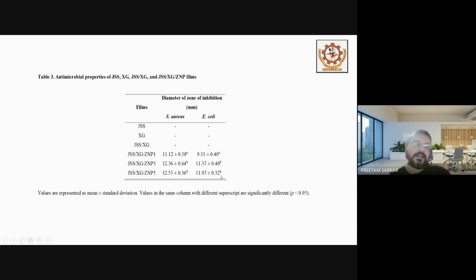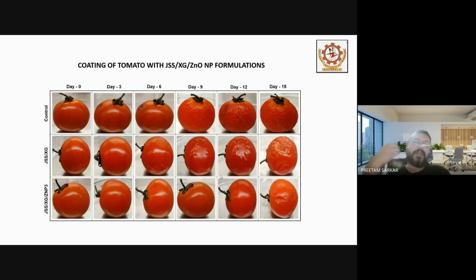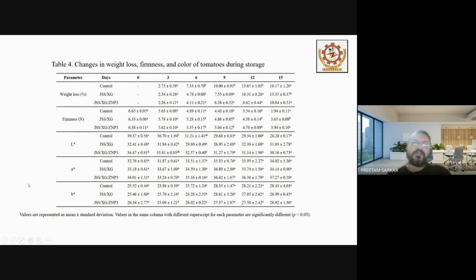Because zinc oxide by nature is quite antimicrobial, we apply that on tomatoes. We use these formulations for coating of tomatoes. There we used banana, here we use tomato, and we studied for 15 days at 3-day intervals. Again, we have 3 samples: control, JSSXG 1:1 ratio, and JSSXG with 3% zinc oxide nanoparticles. We could reduce weight loss, improve the firmness values, and also keep the color properties of the fruit as close as possible to the control.